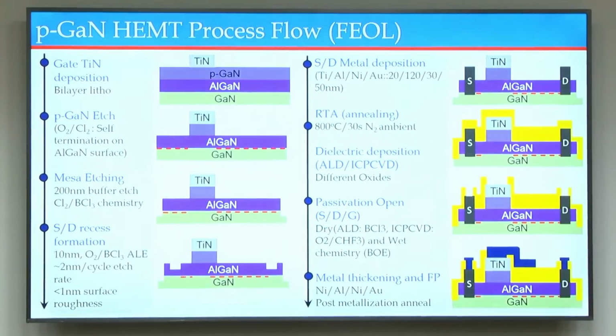Now we figured out after a lot of optimizations that if you do this by masking with a PR, the plasma process damages the top surface of pGaN, which leads to a lot of leakage related issues. On top of that, if you are doing it in 2 steps, then alignment of the top metal with the pGaN also becomes difficult. So if the metal falls outside, you have leakage issues, or if you try to reduce that metal, then the gate control from the sidewall will be pretty weak, and therefore it is going to affect the drive current.